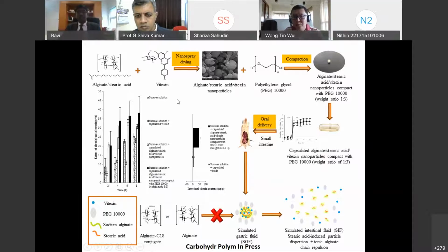We have been researching Ficus deltoidea for anti-diabetic action. Through these few years of research, we have identified vitexins as vital components that lower blood glucose via their alpha-glucosidase inhibitory action. On this note, we then tried to develop nanoparticles as the carrier for vitexins, to deliver them specifically to the intestinal region to interact with the intestinal alpha-glucosidase. How do we do it? We have an alginate and stearic acid mixture, and we mix it with vitexin. We spray dry it into nanoparticles, and subsequently compact the nanoparticles with polyethylene glycol 10,000 into a very small compact, which is inserted into a capsule and administered in vivo for oral anti-diabetic action.